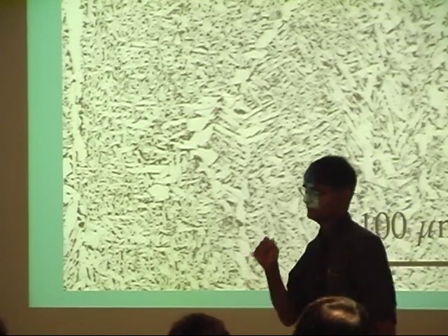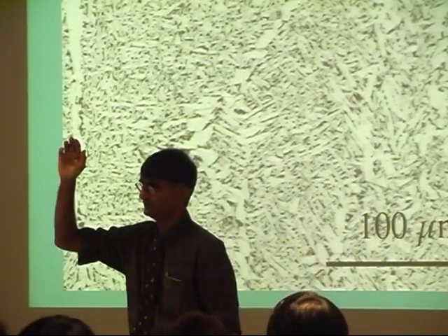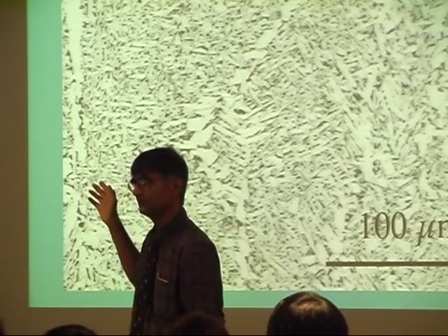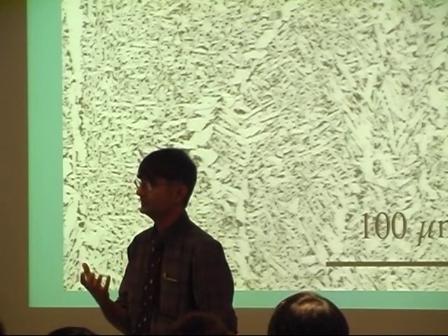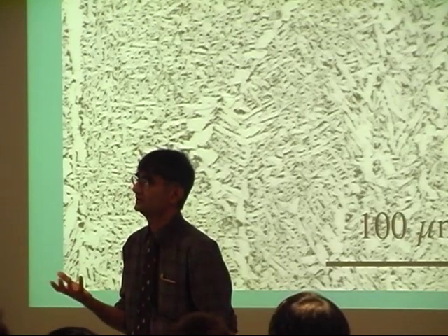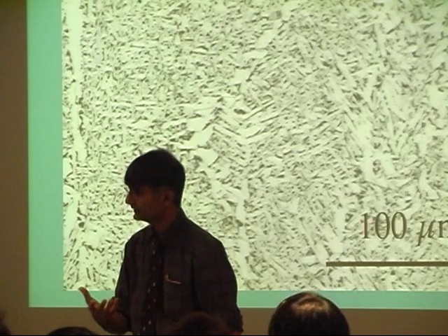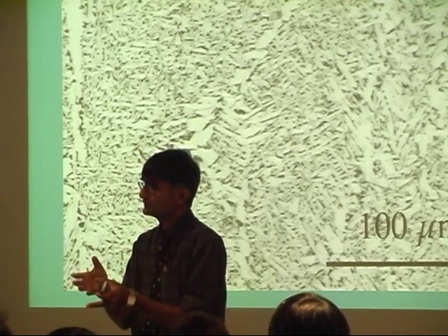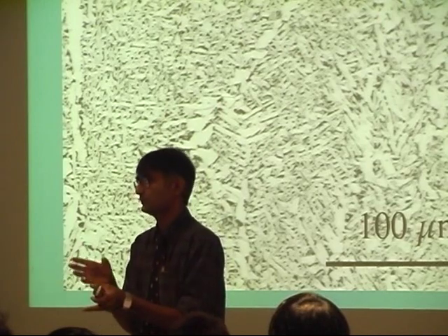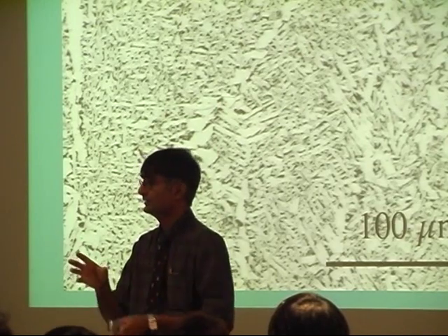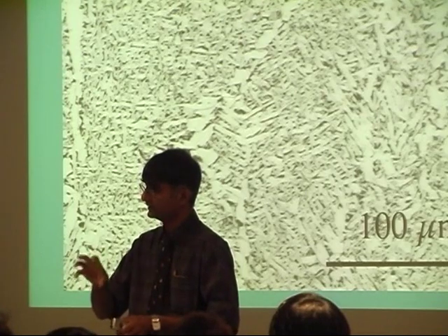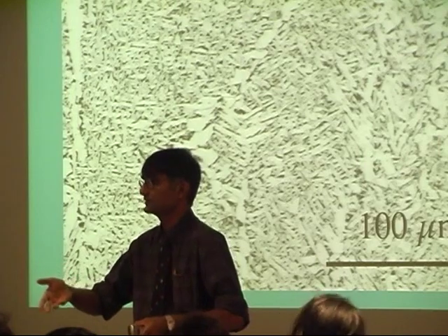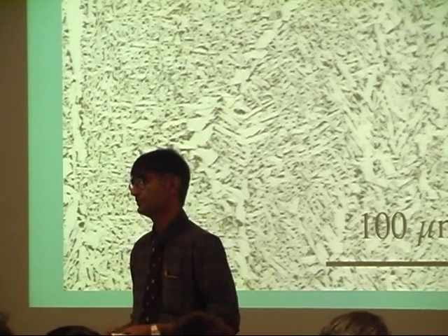And the other thing is, of course, that the strength would go up enormously. Now, here, typically, the required strength is 600 megapascals. If you make it 2.5 gigapascals, you will have other problems. You will have mismatch of strength between the plate and the weld metal. And that will cause a big problem because it's like having a hard region and a soft region. You will focus strain in the heat affected zone, for example, and cause other problems.